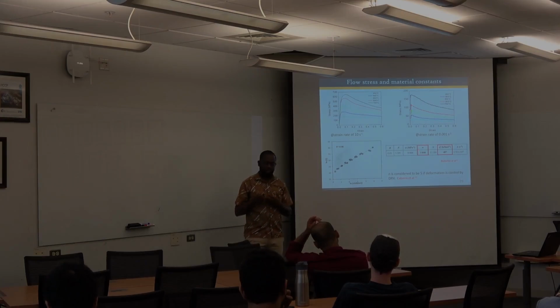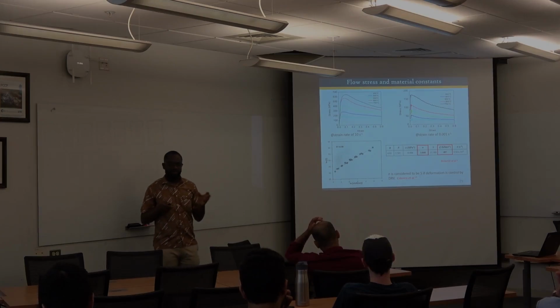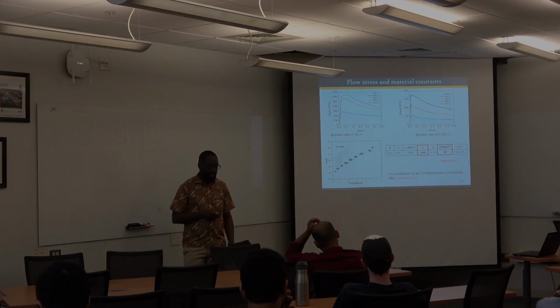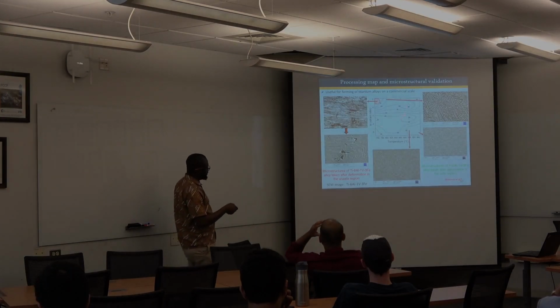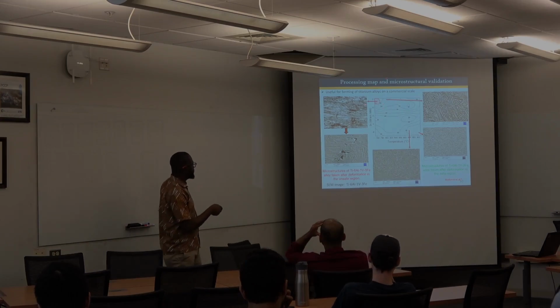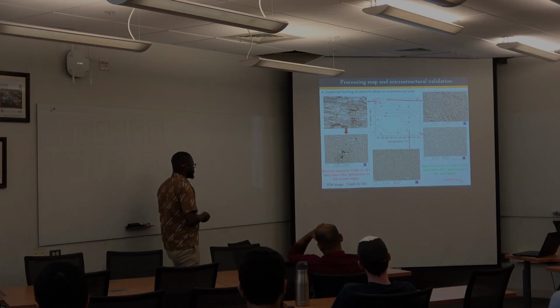So if you apply the constitutive equation, usually when your n is about 5, you think you have more dynamic recovery, so you wouldn't be expecting any globularization or any form of equiaxed microstructure. But because ours was less than 5, we have some hope that we'll probably see that. Dynamic materials modeling can help you come up with a map like this, of different strain rates and temperatures, and you can see regions where you shouldn't even deform the alloys. In that particular region, if you deform the alloy, you would have this kind of defect. And if you take it to STEM, you can see that. So it was really a bad idea to deform under that condition.